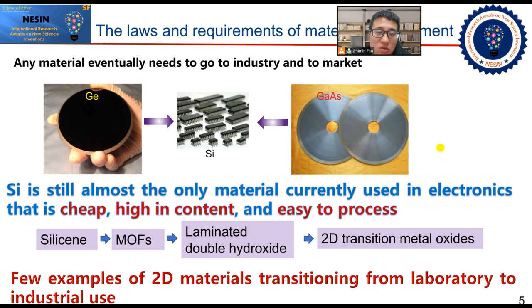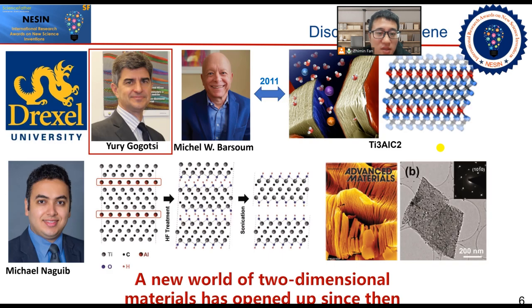Does that mean that the bottleneck of two-dimensional materials cannot be overcome? Gogotsi's graduate students put a MAX phase into hydrofluoric acid, which perfectly etched away the aluminum layer, and then ultrasonically exfoliated it to obtain a two-dimensional MXene, opening up a whole new world of two-dimensional materials. However, the MXene obtained by etching with hydrofluoric acid is multi-layer accordion-shaped, and if you want to get a single layer, you need to peel it by ultrasonic method. But the yield of single layer is very low, and there are many defects.